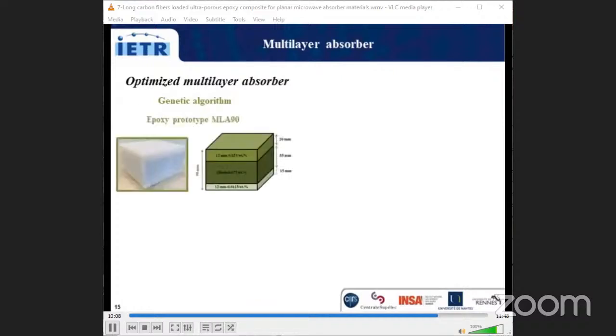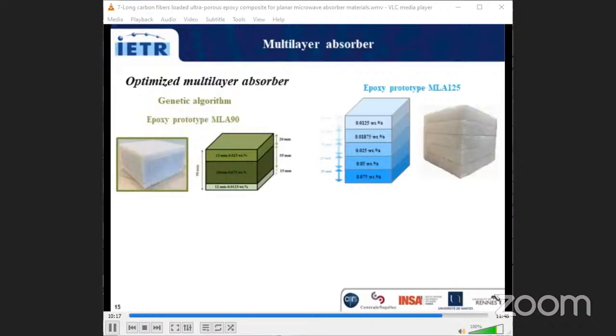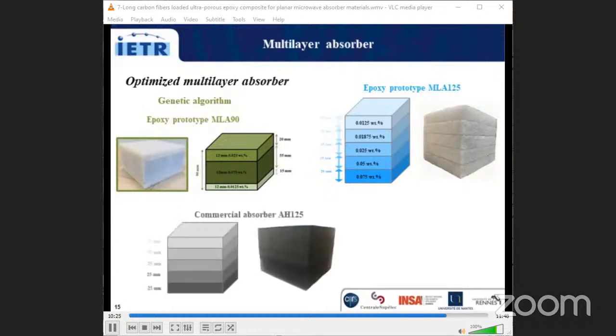The new prototype is made with 3 layers and has a total thickness of 90 millimeters. This prototype will be compared to the epoxy prototype and to the commercial absorber with 125 millimeter thickness. In order to better compare these prototypes by taking into account their reflection coefficients and their thicknesses, a figure of merit was calculated using this formula.